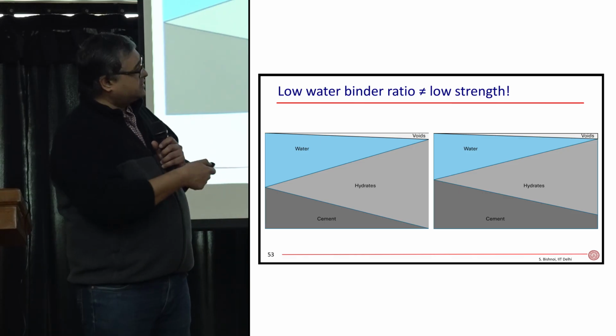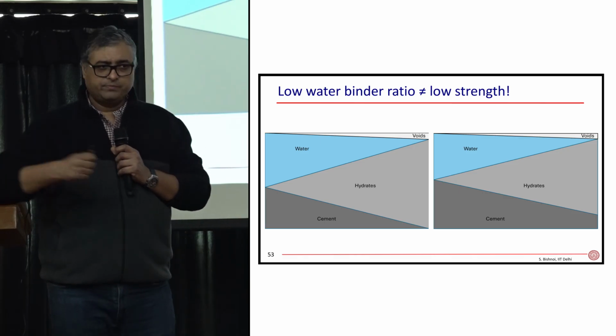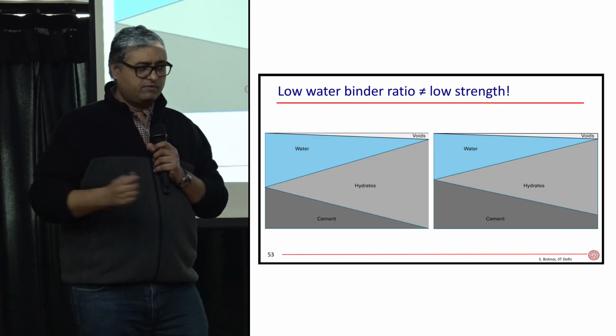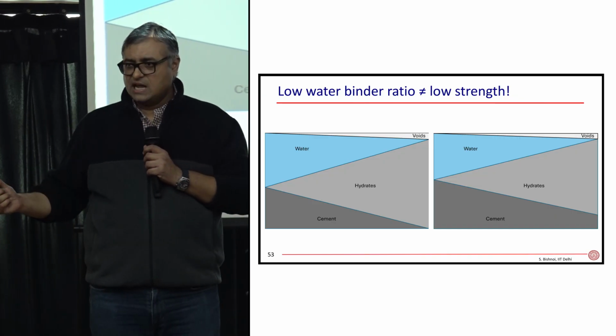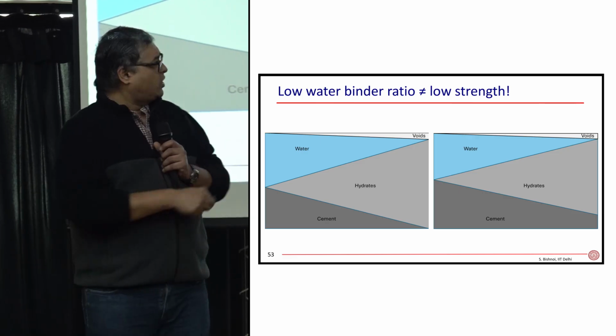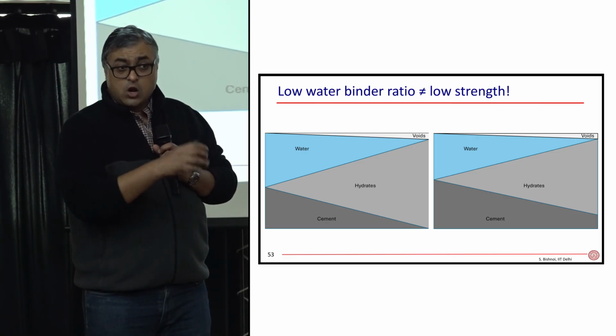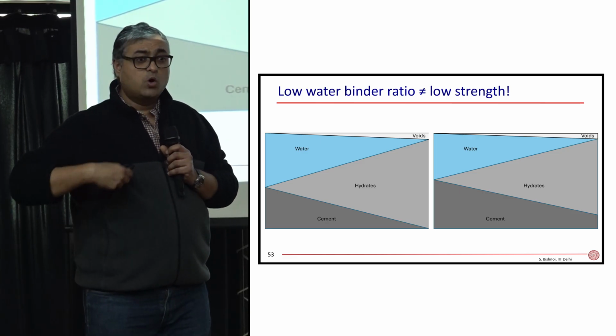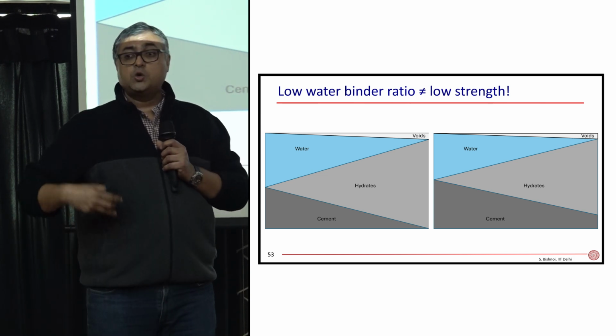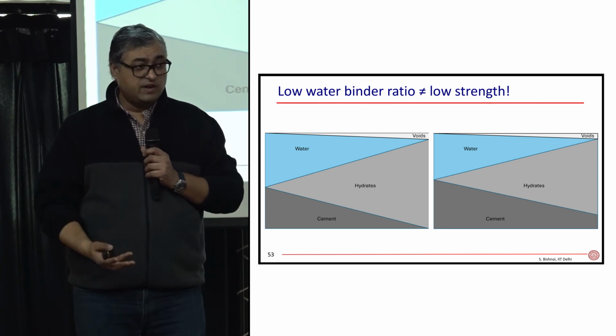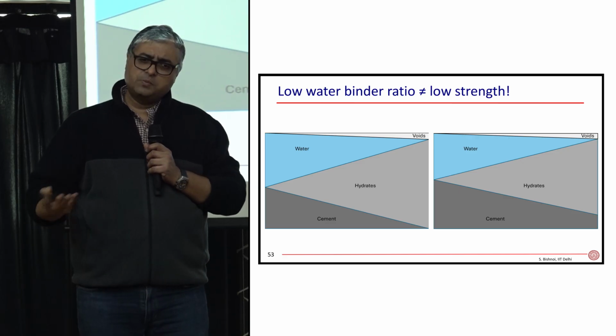But what if I just seal it? I just spray a curing membrane on this concrete with a low water binder ratio—will that help in curing the concrete? There's no water left, the water is consumed. In low water binder ratios, I need to provide more water from outside afterwards to continue the hydration, to continue filling the voids. It's just the opposite of what we do.